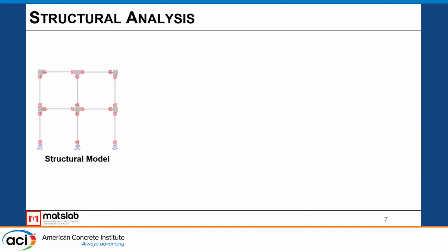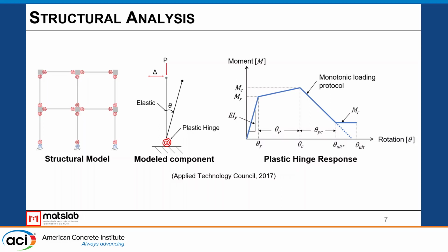So now to work towards understanding how these columns behave at a structural level, we can't necessarily use our finite element simulations. These are computationally expensive for structural analysis. So what we'll typically do is simplify the structure into a spring hinge model. Each component is essentially modeled as an elastic frame element with a rotational spring at the base, and that rotational spring is our moment rotation response of that component. So we can take our finite element results, our moment rotation response, and pick key points along that response. We can then use predictive equations to predict those key control points.